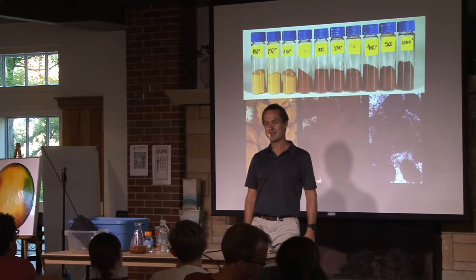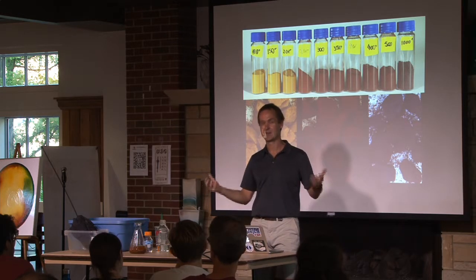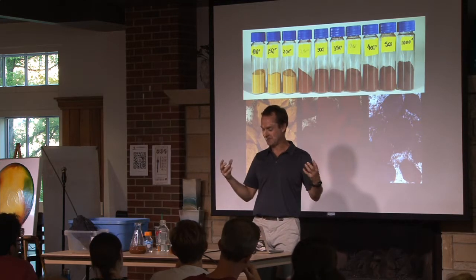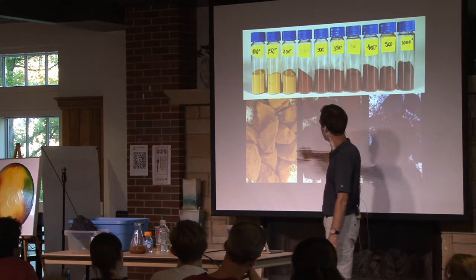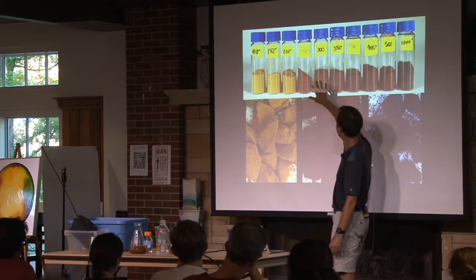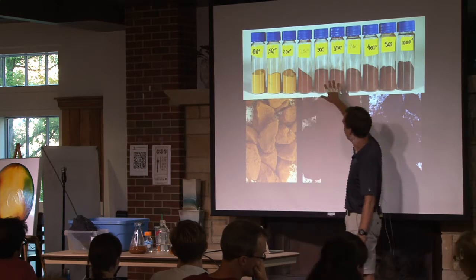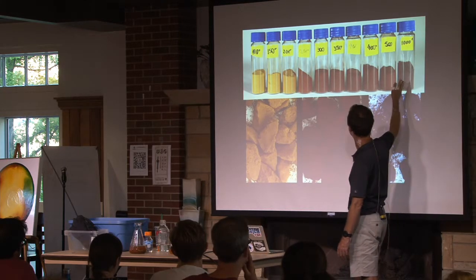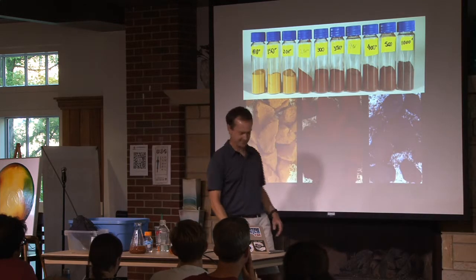Working with an artist, John always came up with crazy ideas. I'd say it's not going to work, but he'd say let's just try it. So next thing I know, I've got all these different samples in ovens and furnaces at different temperatures. Sure enough, when you heat up our raw material from the seep — mostly goethite — it converts into hematite if you heat it high enough. Then he went as high as the furnaces would go, and it turned purple. We don't really know what that is yet, but we're working on it.